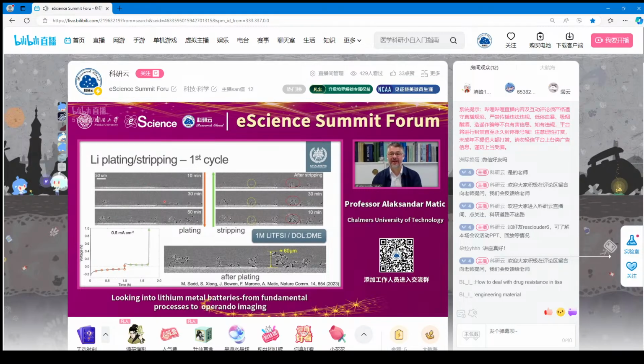And in the end, after plating, so the bottom image here, you can see very tall structures, even up to 60 micrometers formed in this case. When you reverse the current and you start to strip, you can actually see, for instance, if you concentrate on this structure in the yellow circle, how it progressively decreases. So this is successful stripping, also this structure to the left. However, here you can see that this part you don't obtain full stripping, so the process is not fully reversible. So here we have actually the formation of dead lithium.